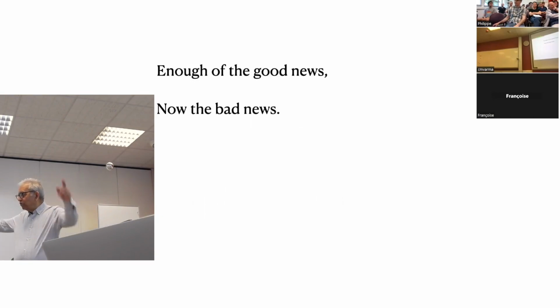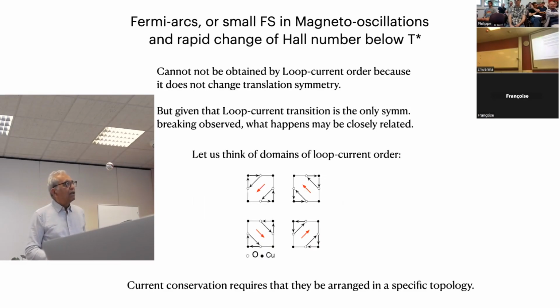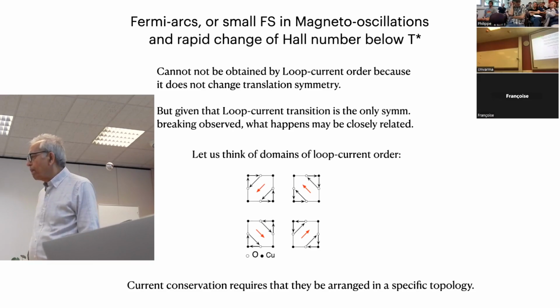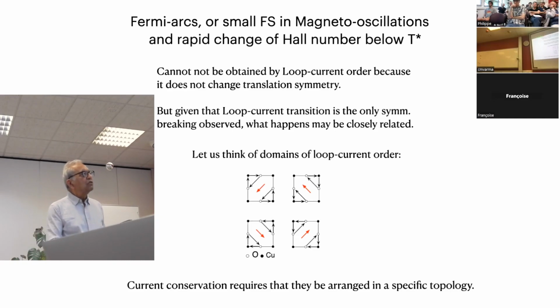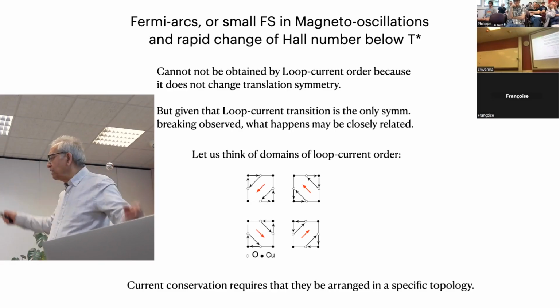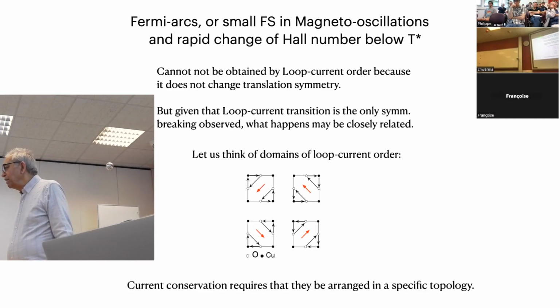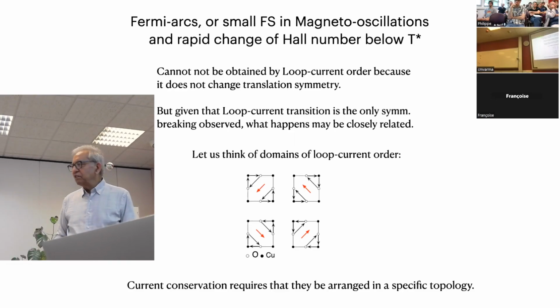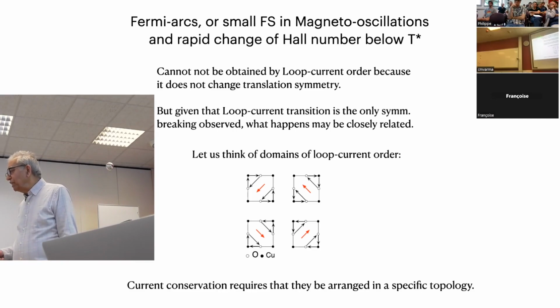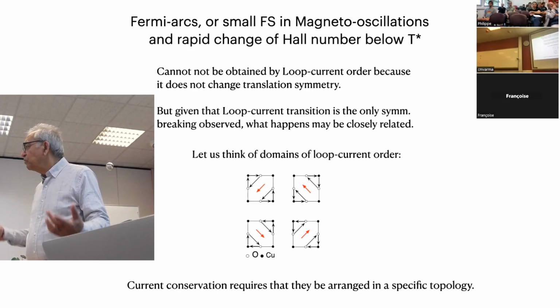Now let me tell you, I'll tell you all the good news, and I've mostly concentrated on this region and the symmetry of this phase, and now the bad news. What's been observed in the last 10 years is that not only is there a diminution of the density of states in the pseudogap phase, there is also, if you do angle-resolved photoemission, you're seeing the whole Fermi surface within the resolution that angle-resolved photoemission is carried out, you see a Fermi arc. And if you do magneto-oscillations, which can see much more closely, it's not really a Fermi arc, it's a closed loop, and you have to surmise that one side of that closed loop is very robust, large amplitude, the other is very small, and how to get that, okay?